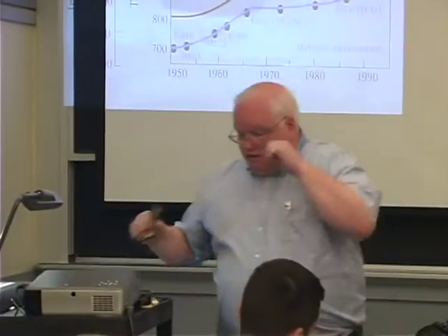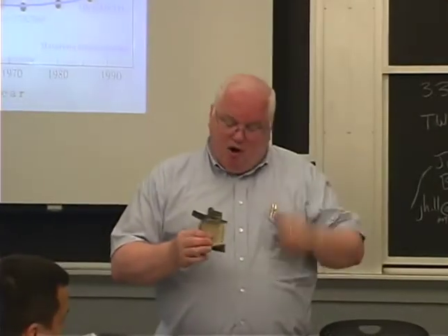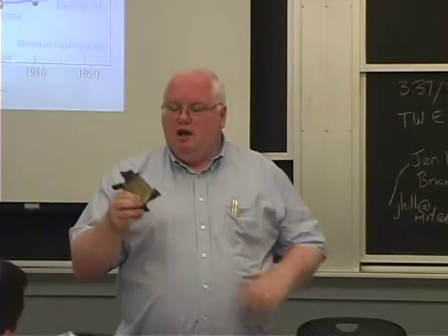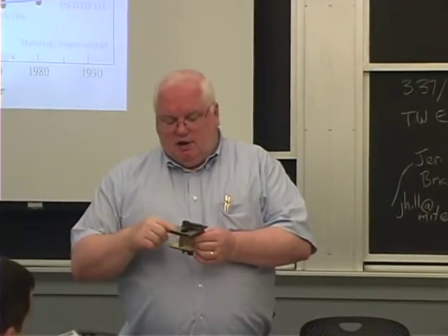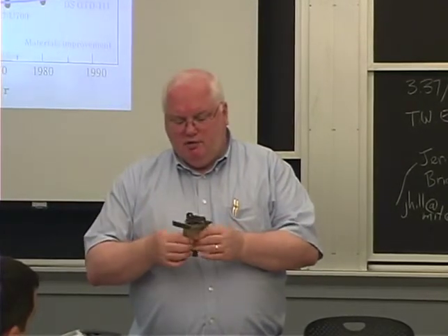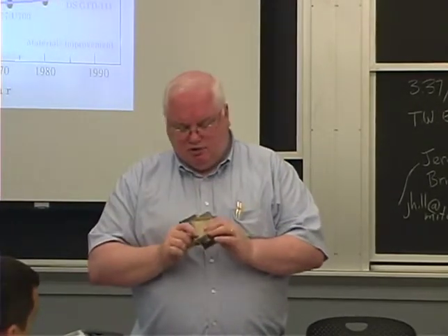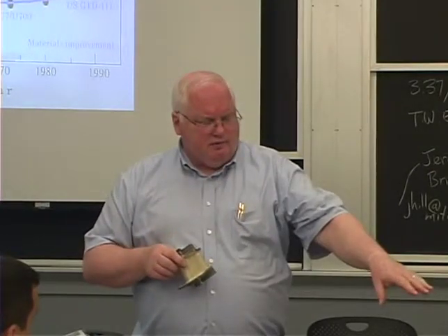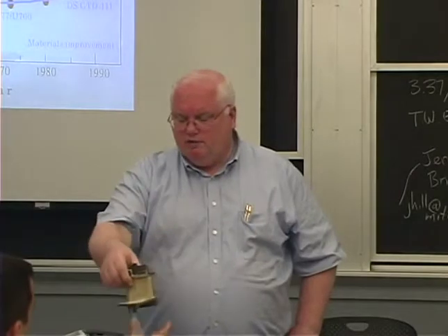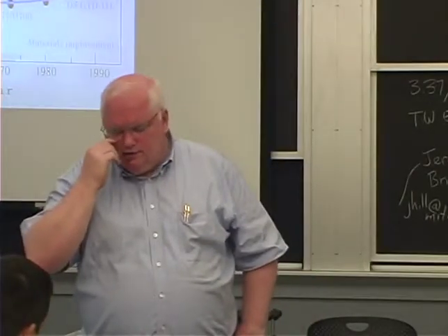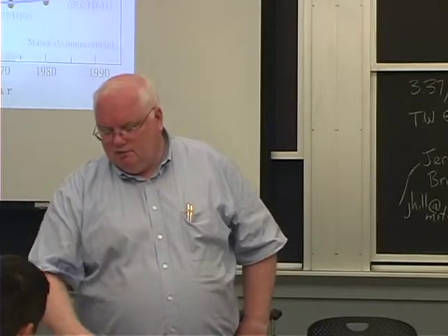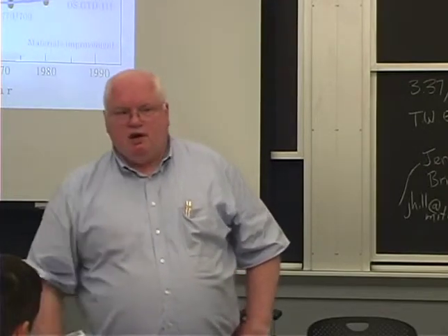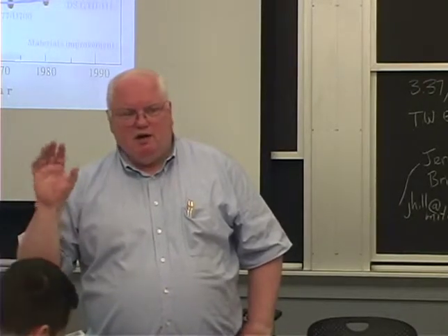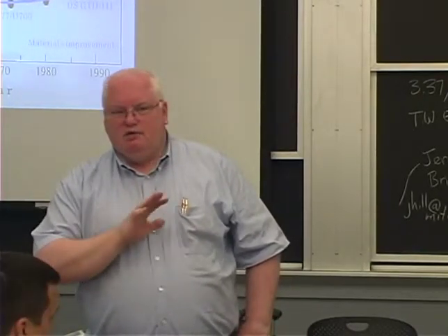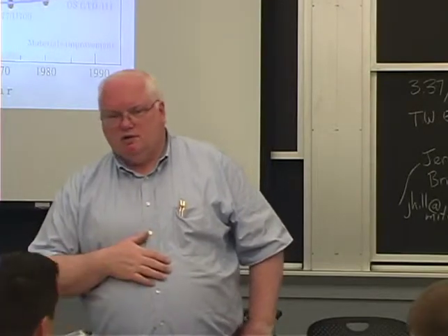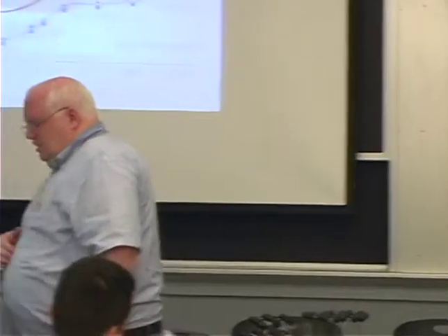And in fact, that's a rotor part. This is a stator part, and this one actually has ceramic coating on it. Has even more cooling passages, and so you have cooling air coming through. That one's a single crystal. This one, I'm not sure if it's a single crystal or not. That came out of either a 747 type engine or a Pratt & Whitney that goes in a 747 or a 757 type of engine, Boeing jet type of engine. That's a stator. This has got a ceramic coating on there because the radiant heat flux is getting to be severe enough that you can damage the surface, so they use ceramic coatings. And that's done by plasma spraying kind of coating technology.